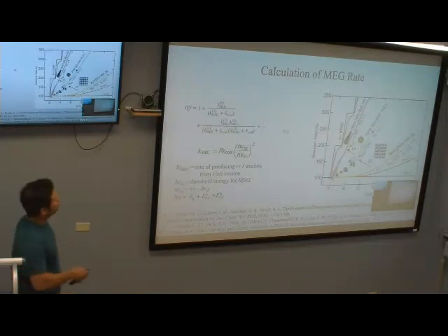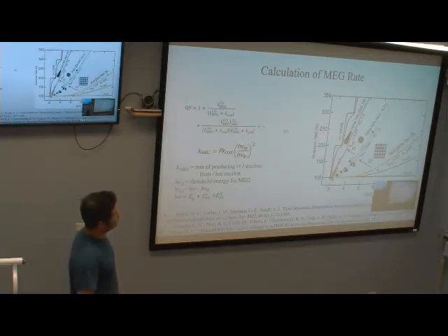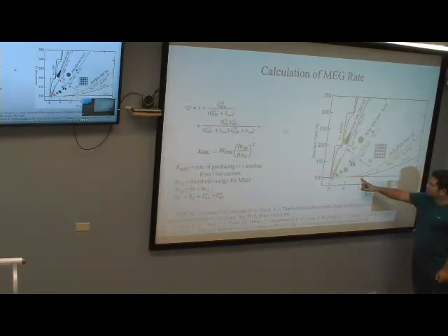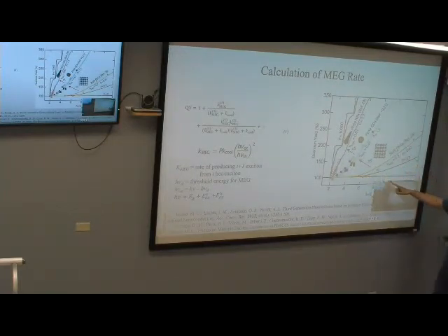So if you plot these equations, this line is plotted for very different compounds. This line, P equal to 0.03, is compared to the bulk material. That means MEG only starts after exciting at about 5 to 6 times the band gap energy. So if you want to get the multi-exciton, you need to excite at a very high energy.